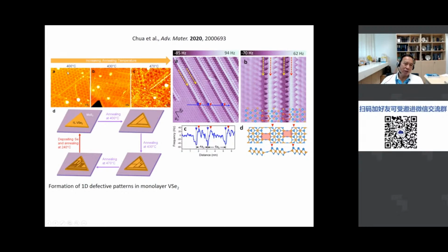And if you anneal it to 400 degrees centigrade, you can see these line defects starting to appear. And when she annealed it to 430 and then 470, there's an increase in density of line defects, shown diagrammatically in the schematic below. So you can increase these line defects just by annealing. They form triangles because it's just reflecting the hexagonal symmetry of the vanadium diselenide.